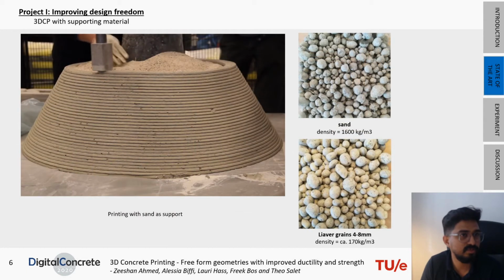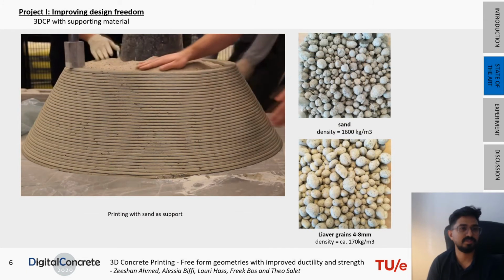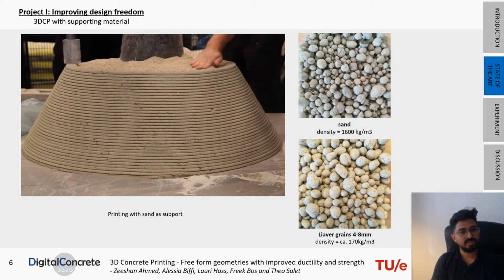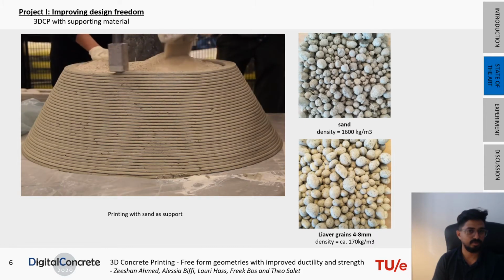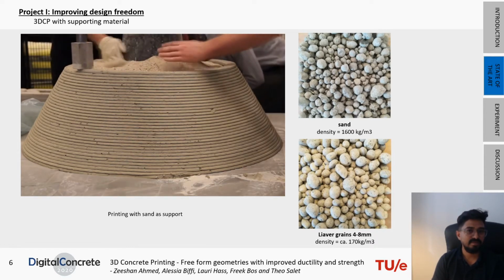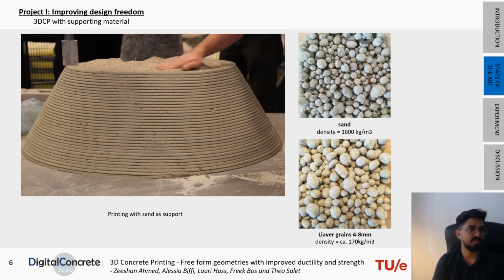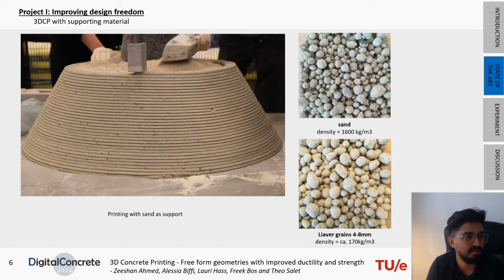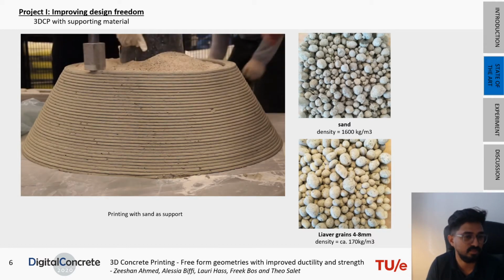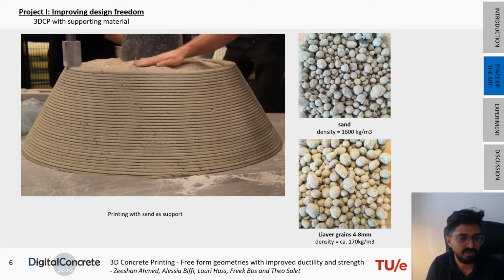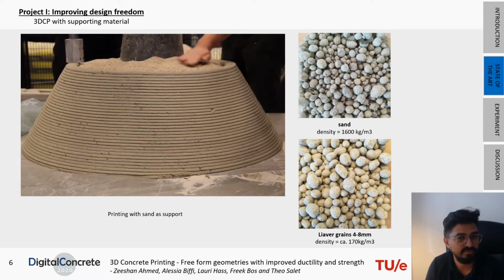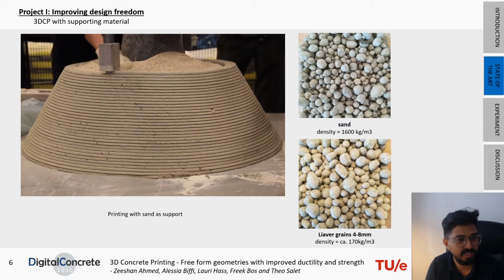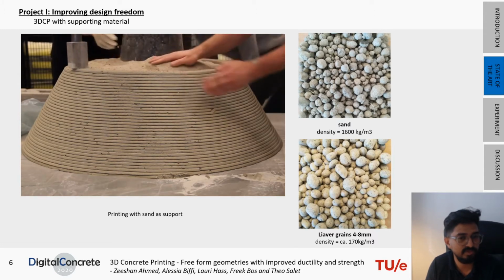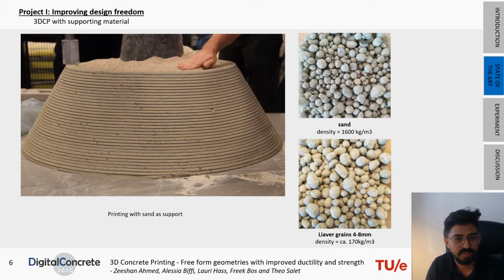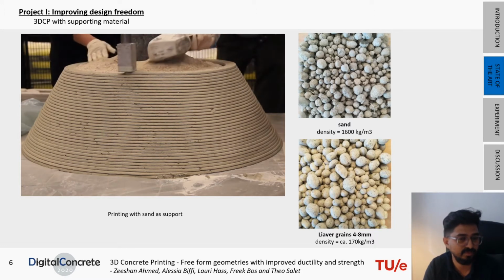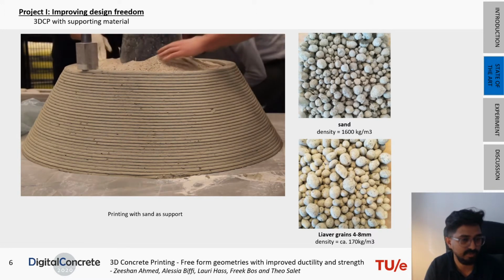Talking about the first project, which is 3D concrete printing with supporting material, we started this project using sand as a supporting material. But sand having a high density, we realized that we wanted a material with a little less density or less weight to use as an infill material, for which we used lava grains, which are lightweight aggregates used for making lightweight concrete. These lava grains have a density of around 170 kg per cubic meter.